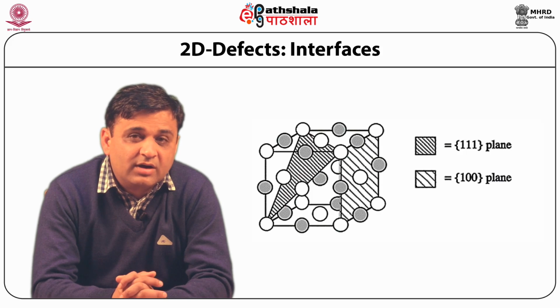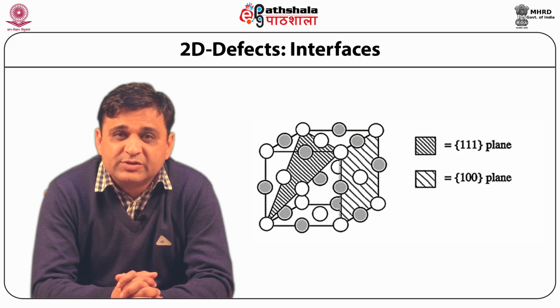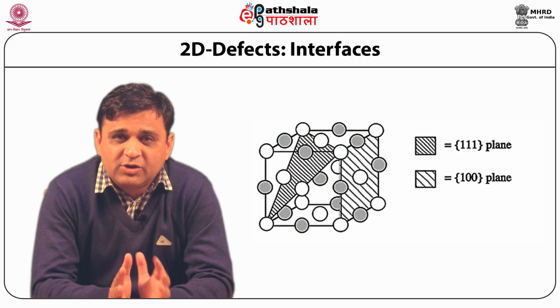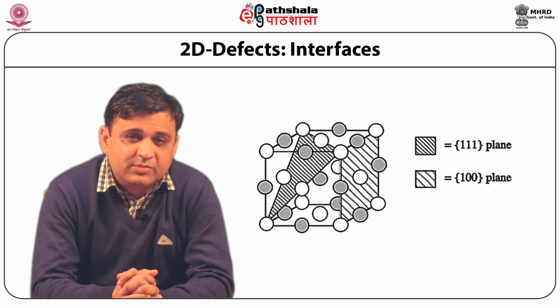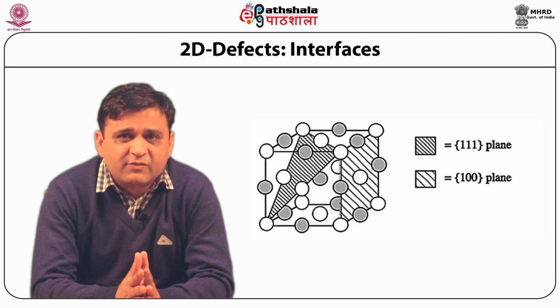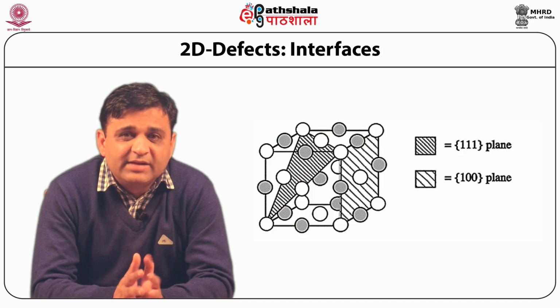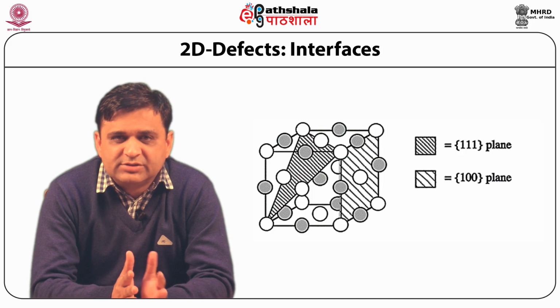In strongly ionic materials, the electrically neutral surfaces, 100, have much lower interfacial tension than the charged surface, such as 111 in the above example. The relative interfacial tension of charged and uncharged surfaces can of course be altered by the addition of surfactants, which are often preferentially attracted to the charged surface.